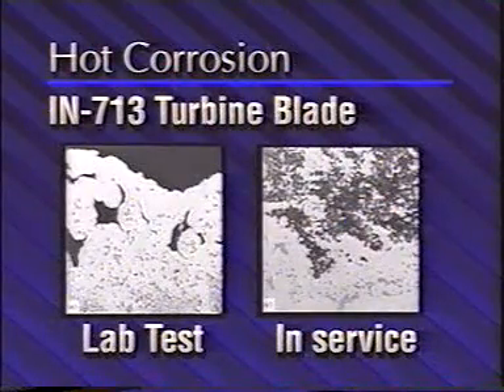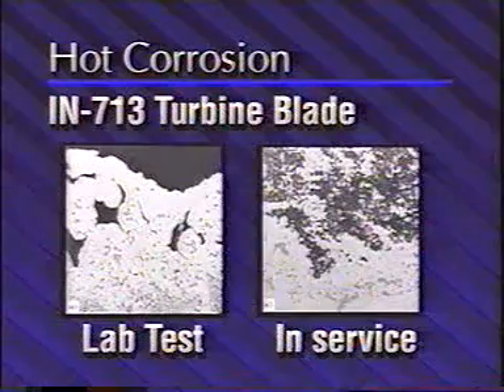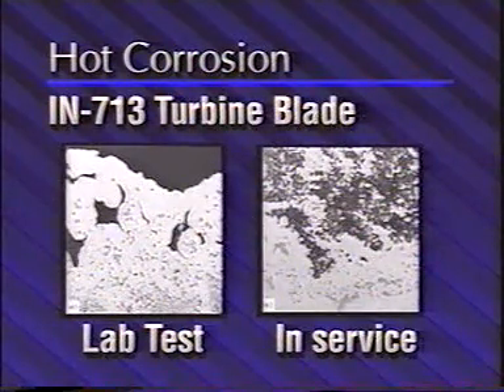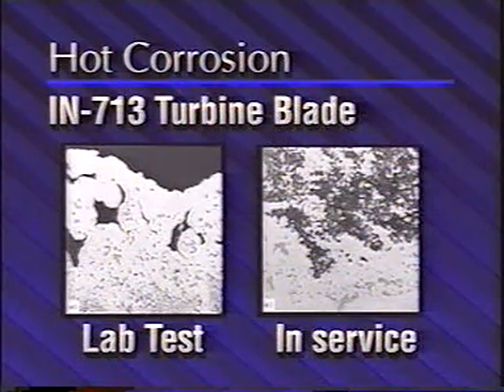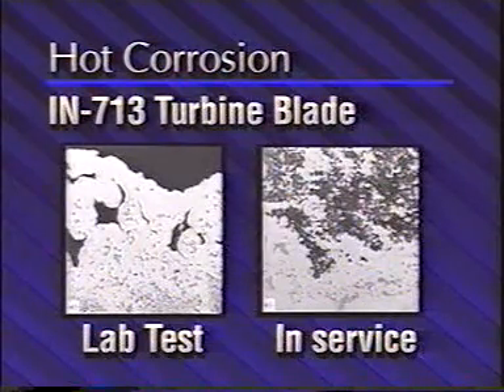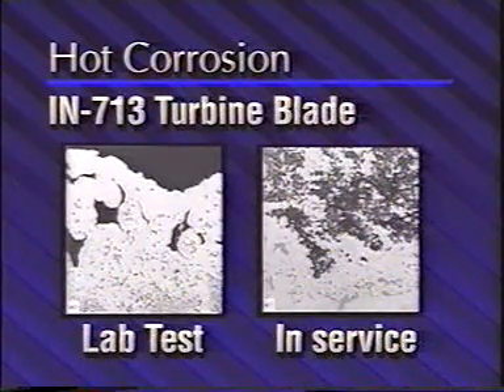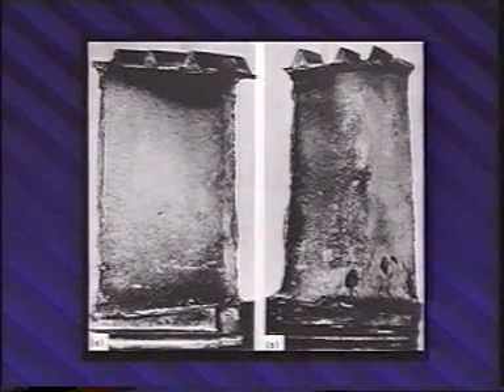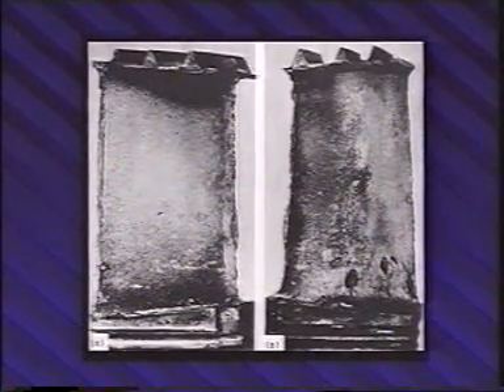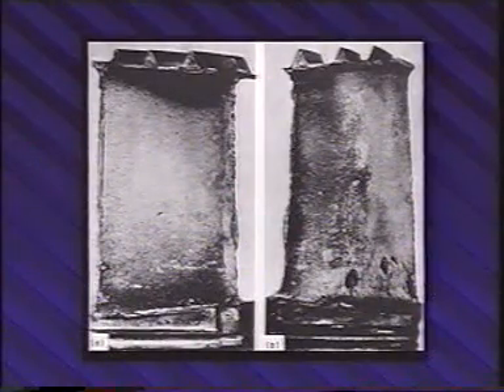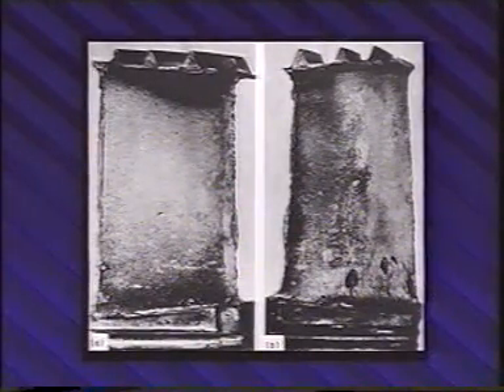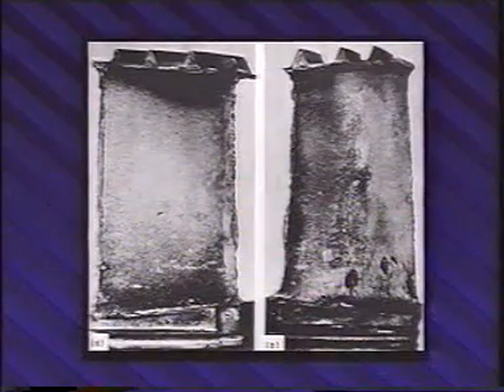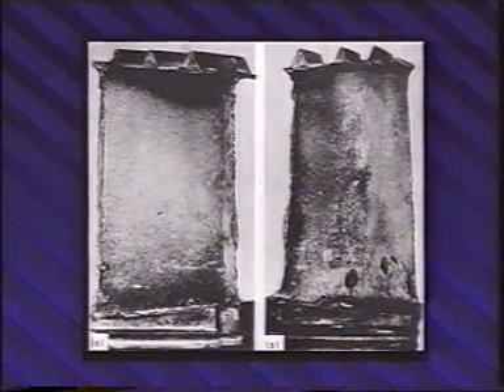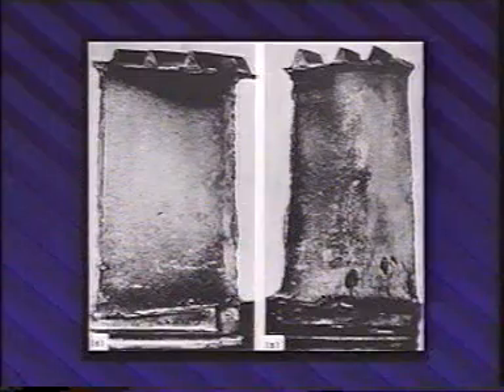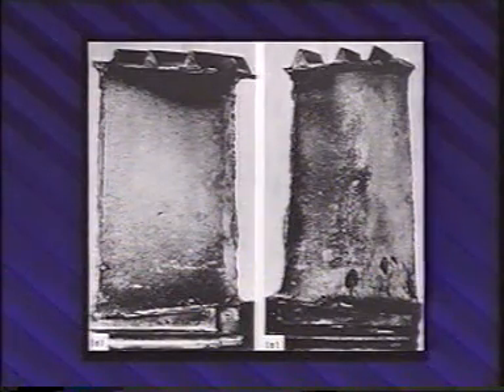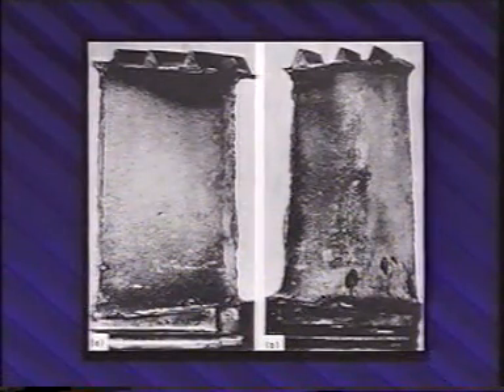Hot corrosion can also attack a coating in a localized area. A localized attack may be the result of variations in the chemical composition of the coatings. The attack can also be the result of corrodants concentrating in a localized area. It is also possible for corrosion-erosion degradation of the coating to occur at one specific location. A good example is the leading edge of a turbine blade, which is exposed to high-temperature, high-velocity gases in the turbine. Subsequently, the base metal is also attacked, requiring premature removal of the component from service.